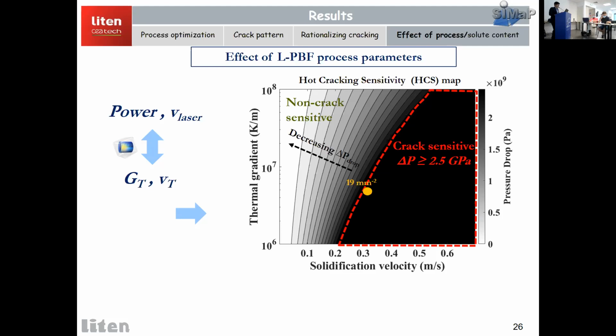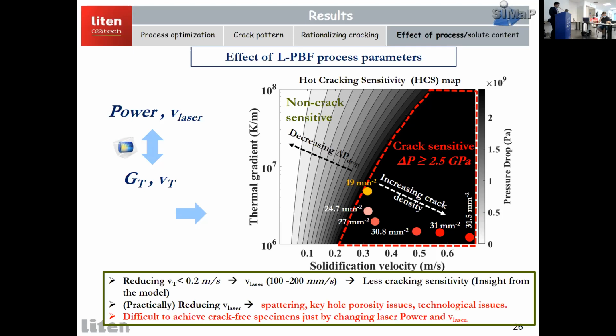If we look at other parameters which we studied, we see an increase in crack density as we move away from the interface. So the experimental points are qualitatively in agreement with what we have estimated with the HCS map. One inference from this HCS map can be that by decreasing the solidification velocity to 0.2 meters per second, we can be in the non-crack sensitive zone. To achieve that, we need laser speeds of around 100 to 200 millimeters per second, which is quite low. So these are insights from the model.